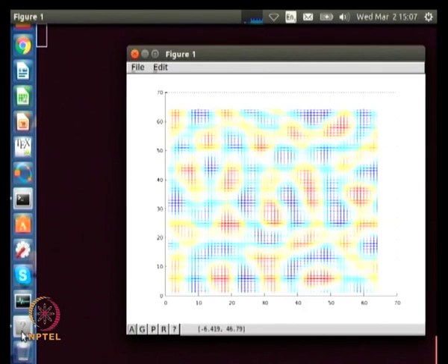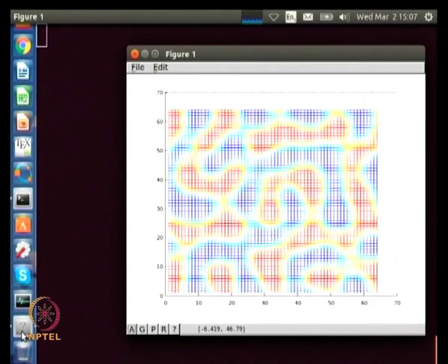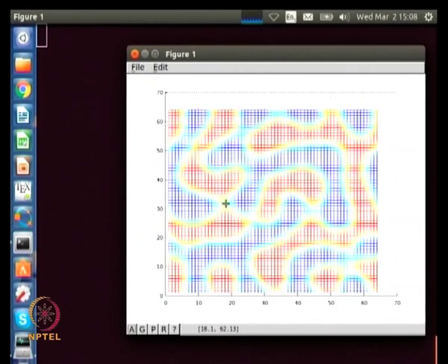So, it is becoming so you can see all A rich regions and B rich regions forming, and it is evolving, because we are now going to longer time. You can see that these are coalescing. Here at this point they are all coalescing. And this is becoming 1, and this is probably going to become 1 together. So, you have this interpenetrating microstructure that is coming up, that is very very typical of spinodal decomposition.